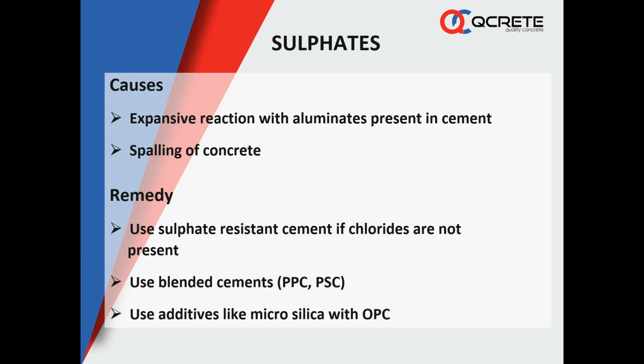So what we suggest is that you should go in for a blended cement. GGBS is the best. You can go for ordinary Portland cement with GGBS. For a sewerage outfall project in Mumbai, a concrete tunnel taken 10 kilometers inside the sea, when they made the segments, they made M40 concrete with 70% GGBS and 30% ordinary Portland cement. That was the best one because the sewage has both chlorides and sulfates, and the seawater on the external surface is full of chlorides. So it was the best to resist the attack from both chlorides and sulfates.